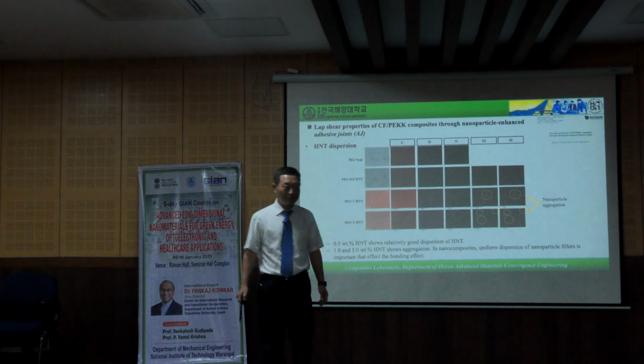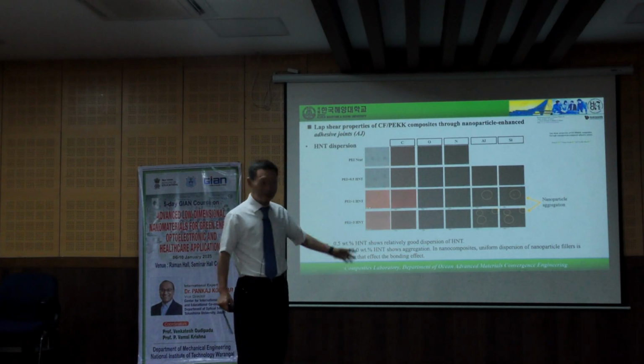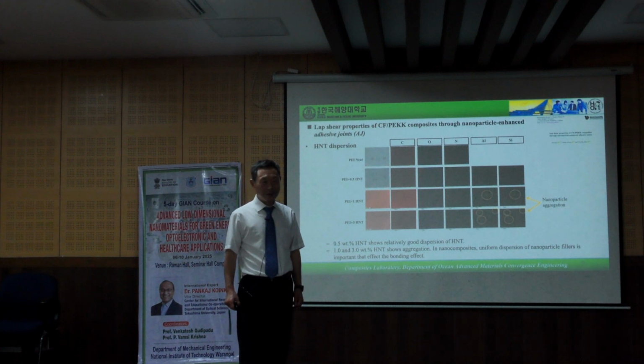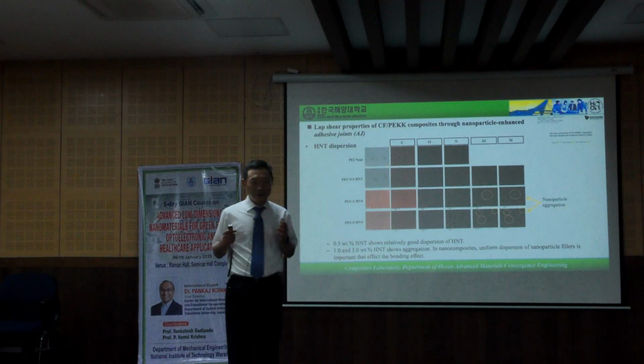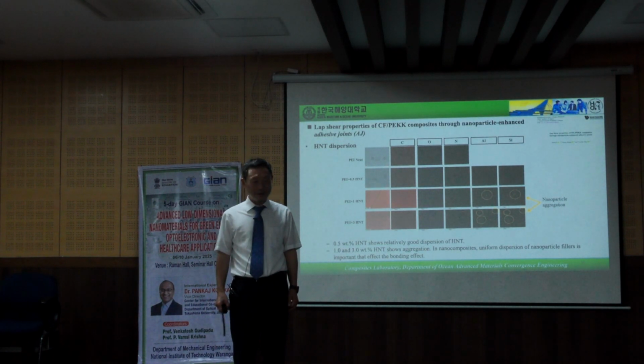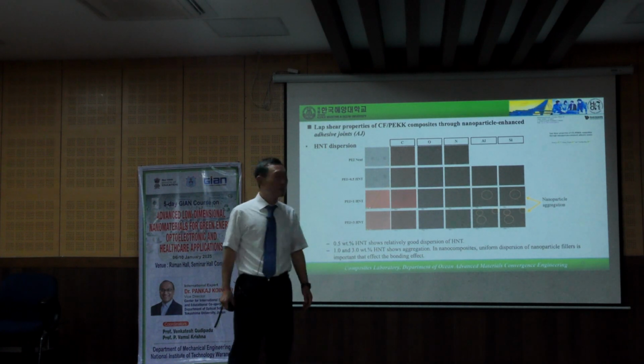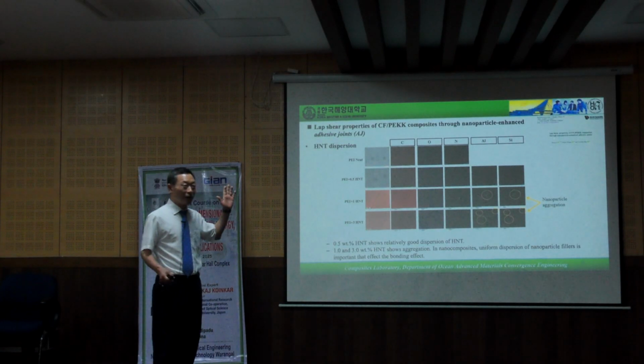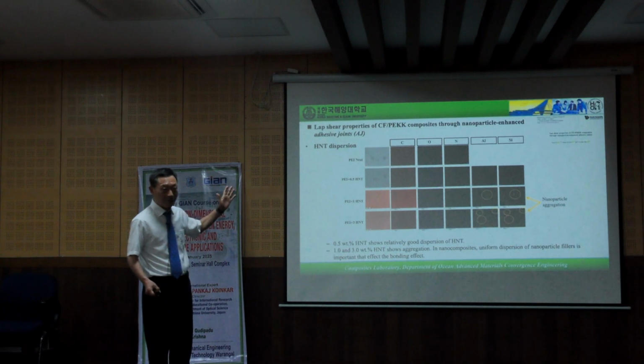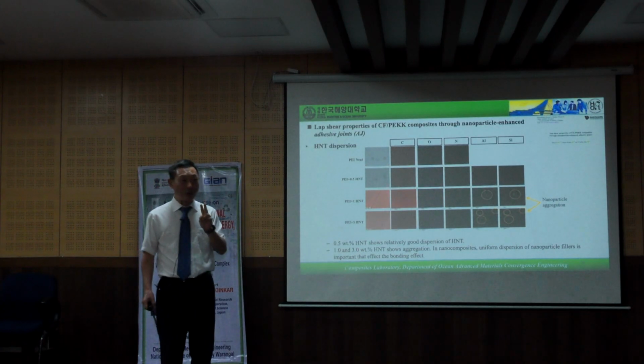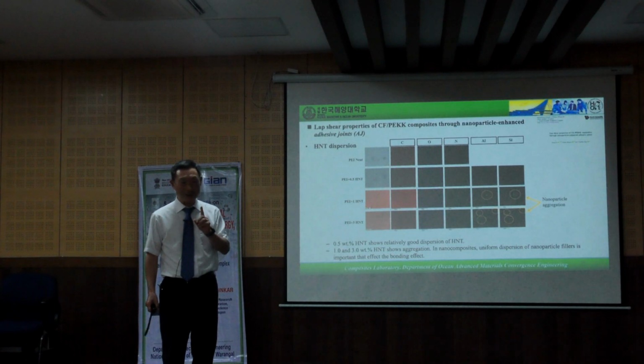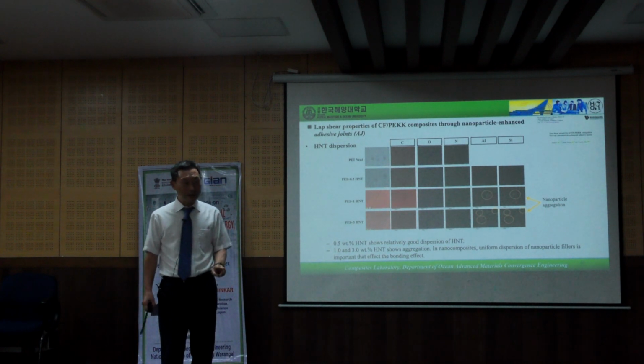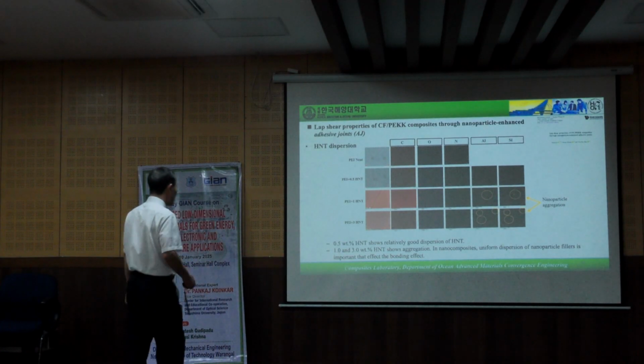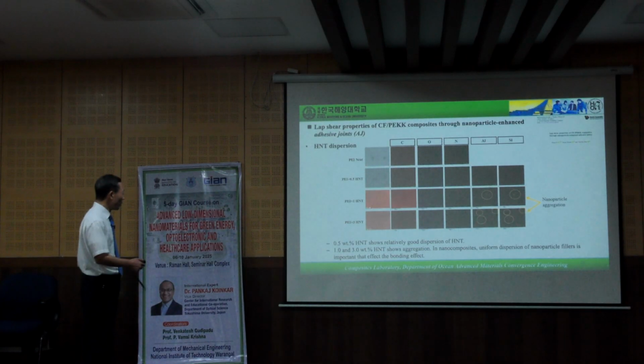This is a very big problem in incorporating it into the composite material, because this kind of aggregation causes stress concentration. But this is a big problem, so we have to solve it. So, in case of this aggregation situation, two stages of aggregation will occur. First stage will be caused by van der Waals force, and second, chemical shrinkage. So, two types will occur. So, 0.5 and 1.0 and 3%. The situation is like this.